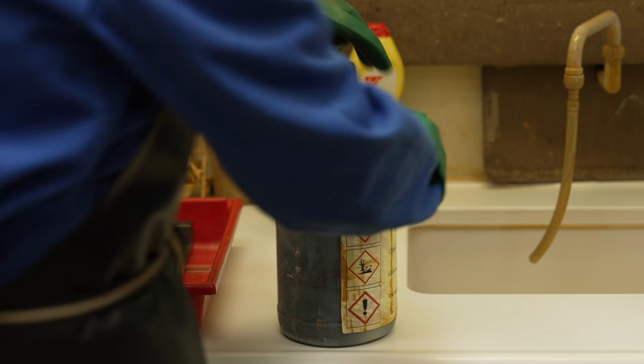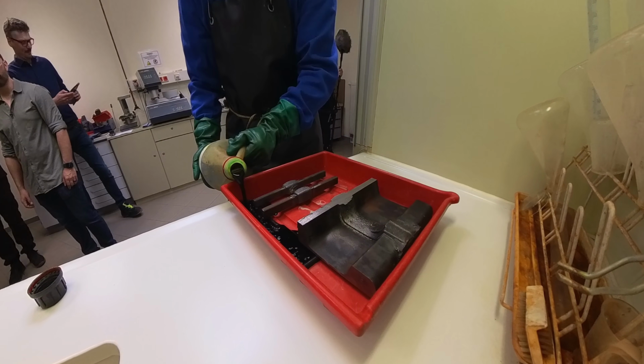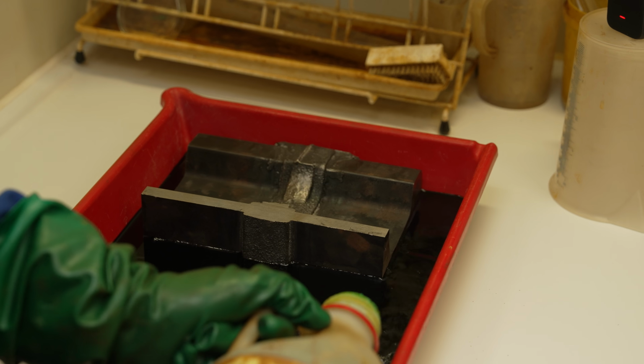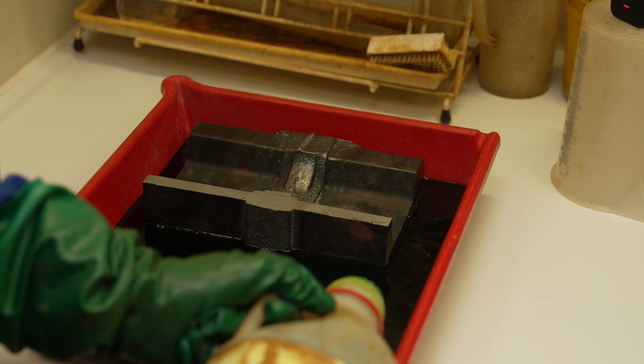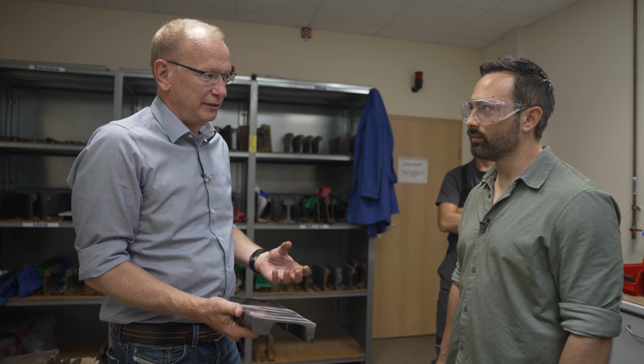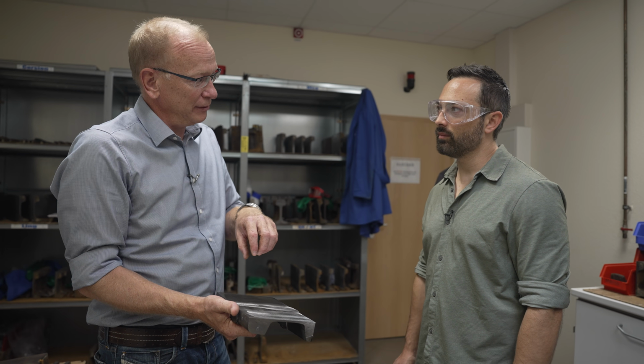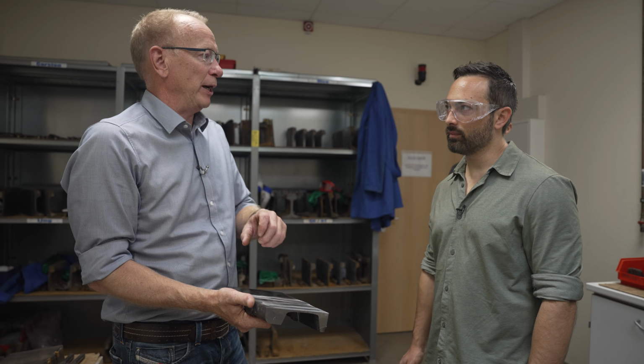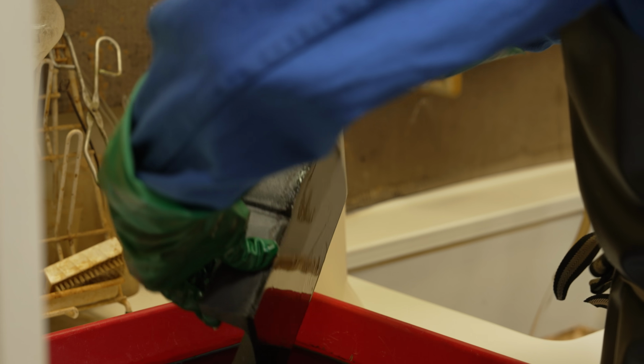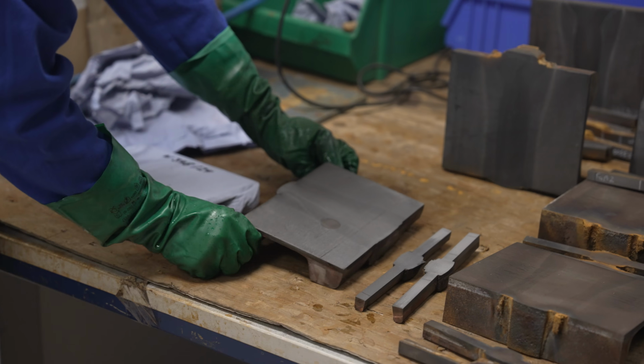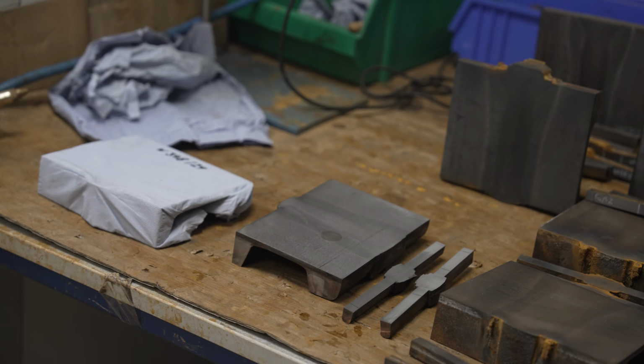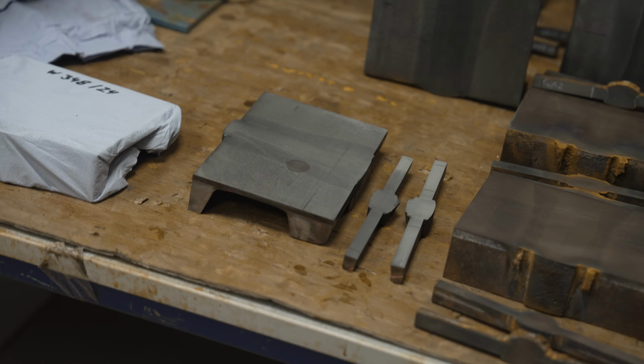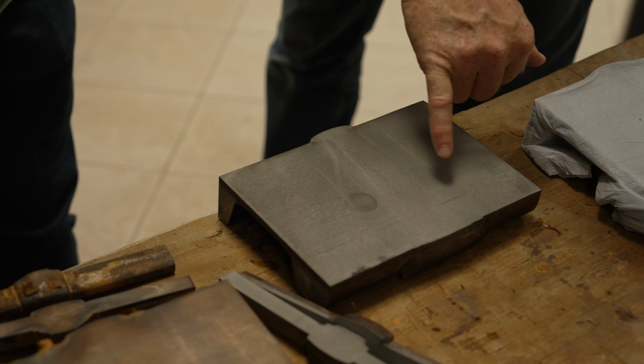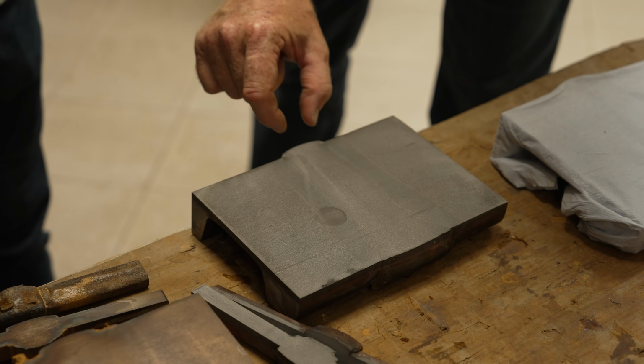What does the acid do to the surface? The acid attacks the steel. But because the orientation of the crystals inside the steel is not the same, the acid attacks it not in the same way everywhere. And because this is different, you can see different structures. You can see some fine structures in the rail, in the heat-affected zone, and in, let's say, the fusion zone.